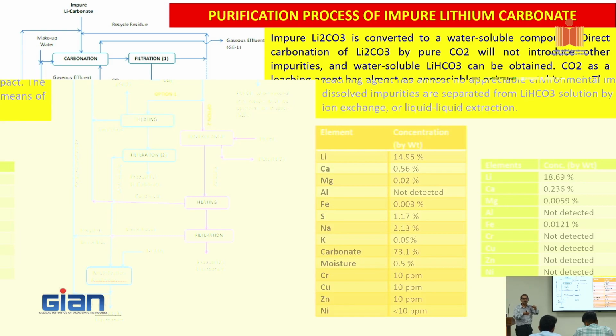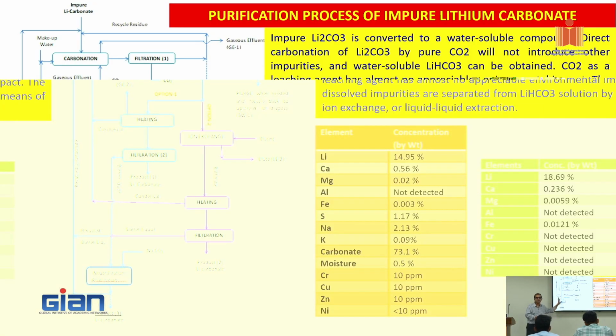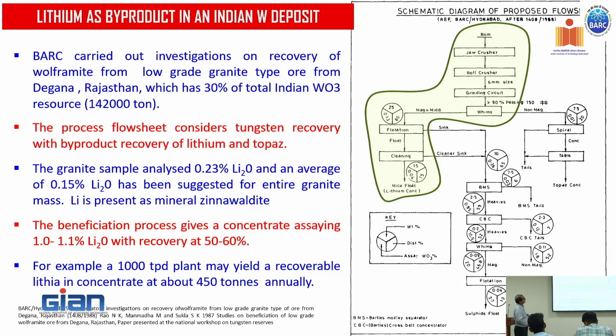Again, it consists of principally redissolution, evaporation or ion exchange. Ion exchange, that is by using an adsorbent and removing lithium selectively. Evaporation is the other way of increasing the concentration, and reprecipitation as lithium carbonate. This is how we take the lithium from spodumene. Now, as a byproduct where it is present, if you take the tungsten ores of Rajasthan, along with the